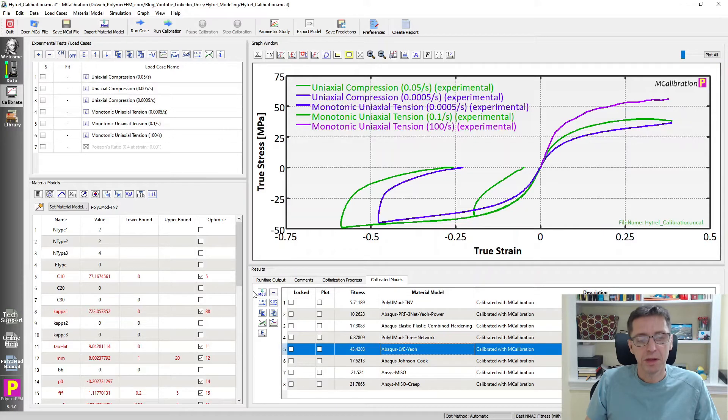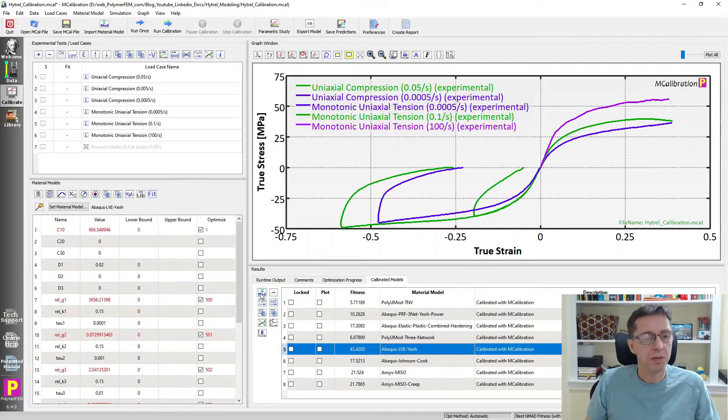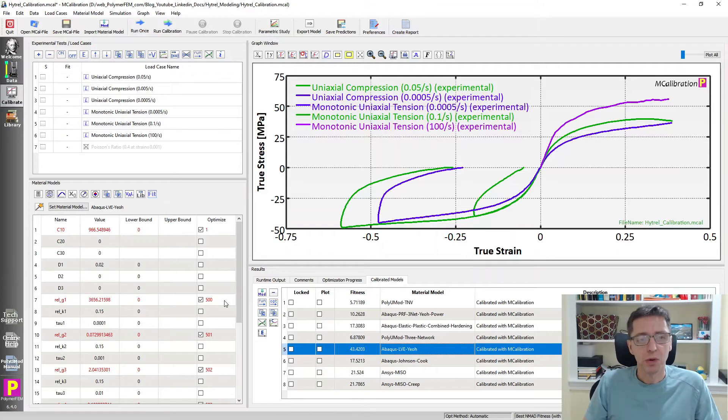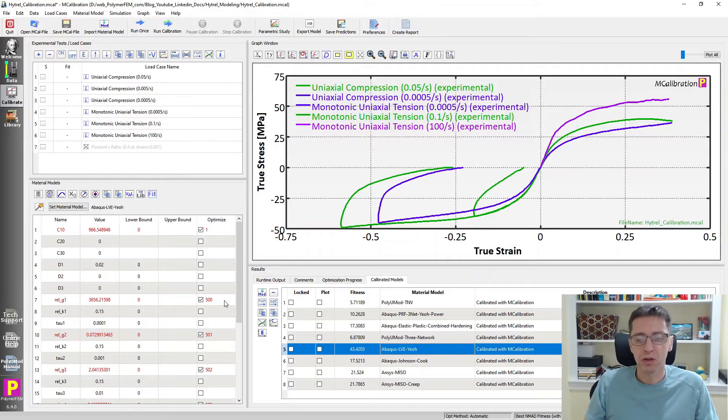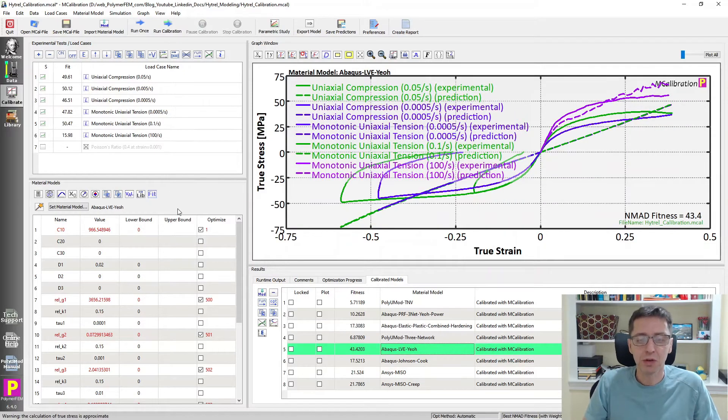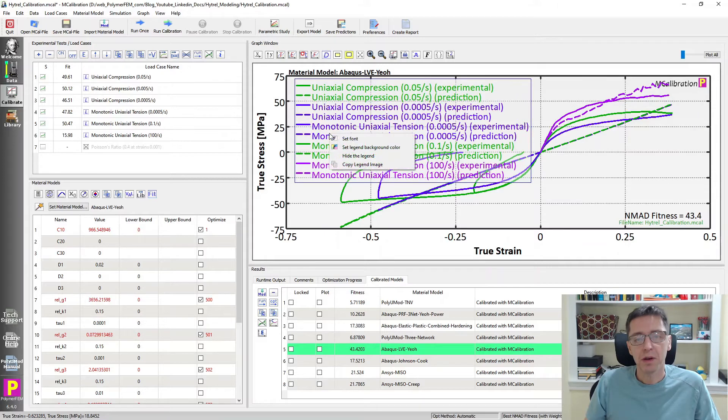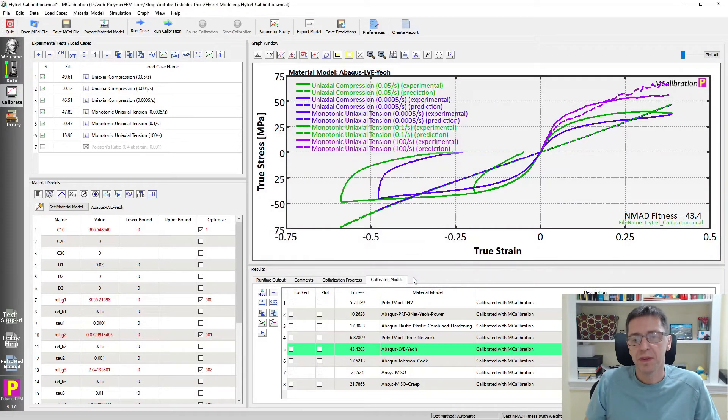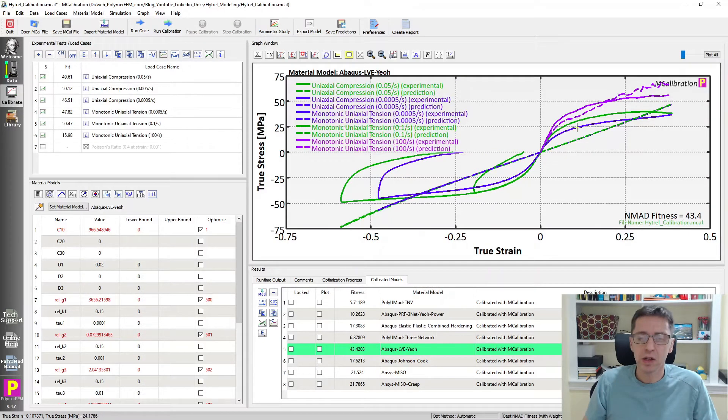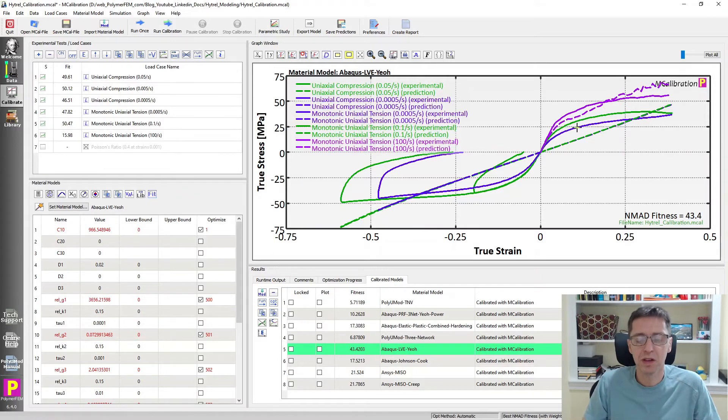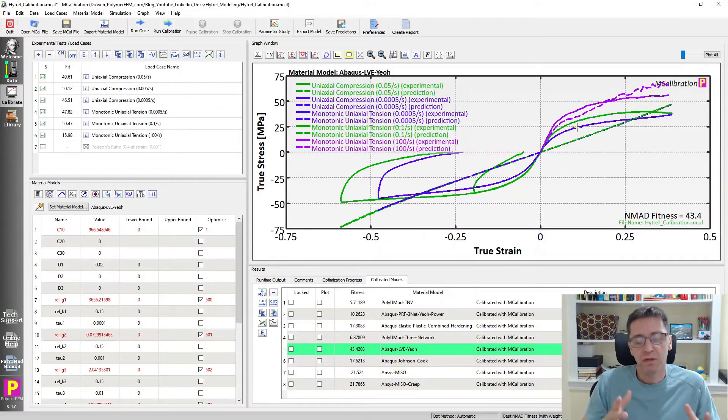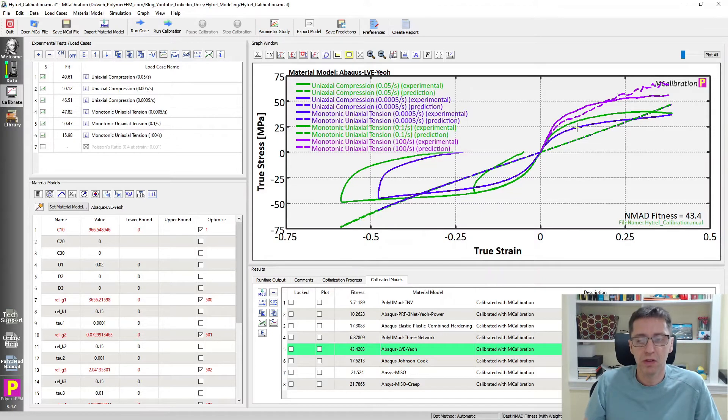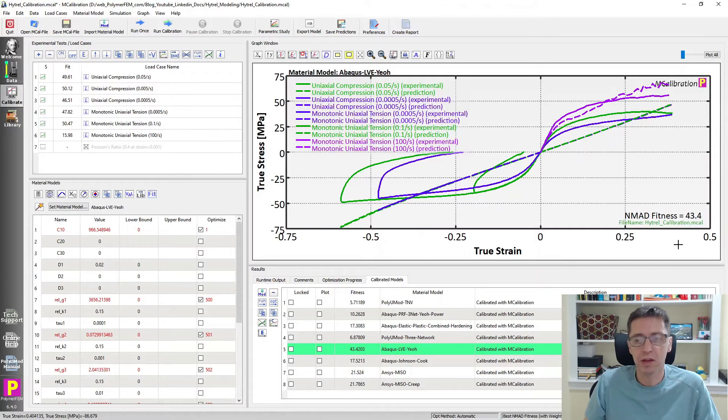So I have already calibrated a few models here to help me out a little bit. Let me pick something very simple to start with. That's an Abaqus linear viscoelastic material model. It doesn't matter if it's Abaqus or ANSYS or some other FE. So linear viscoelasticity in general is a terrible choice here because I'm going to minimize the size or reduce the size of this legend here. We'll see. Because this material actually undergoes permanent deformation, undergoes some plasticity. And as a rule of thumb, you should remember this, that when you're analyzing a polymer beyond the onset of plastic deformation, you should really never use linear viscoelasticity.